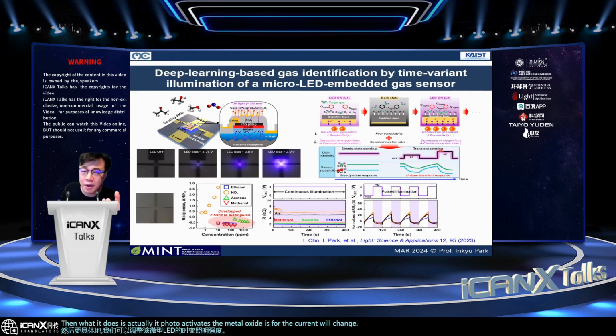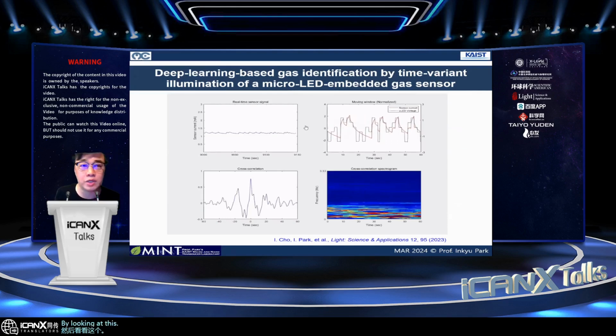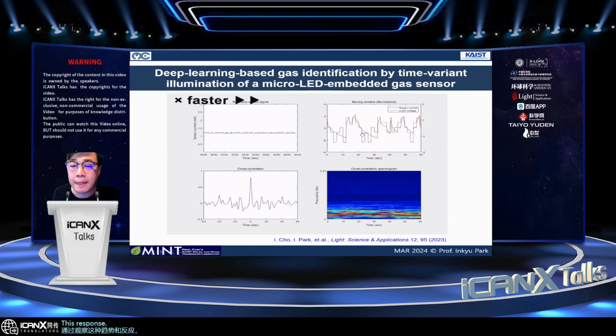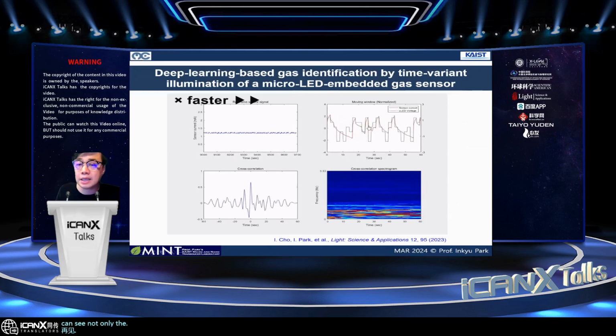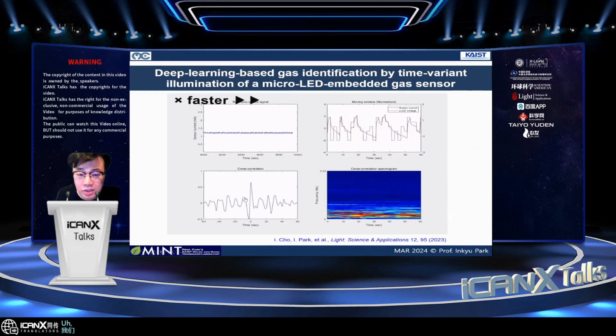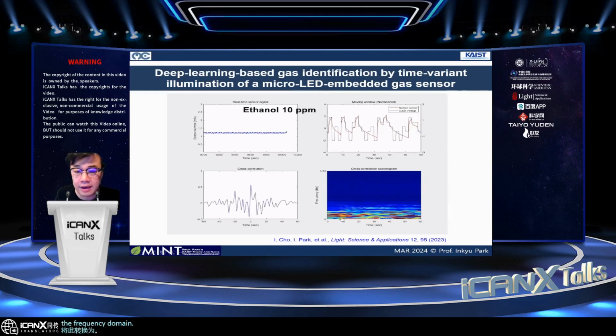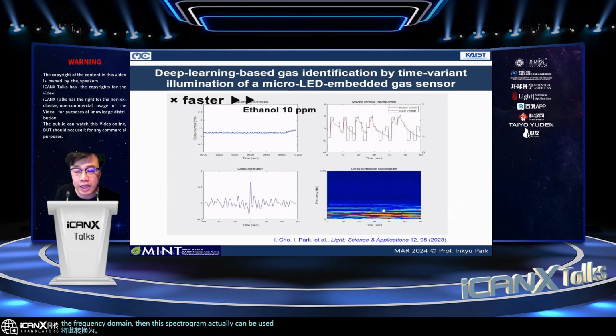This photocurrent will change with the varying illumination intensity, but the transient profile is dependent on and determined by the type and concentration of the target gases in the surrounding. So by analyzing this transient shape, we can tell what type of gas and what concentration exist. A bit more specifically, we use this kind of transient response of the gas sensors, and you can see not only the time response, but we convert this to the frequency domain. Then this spectrogram can be used for the training.